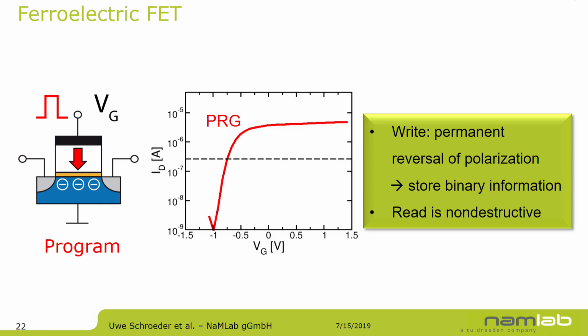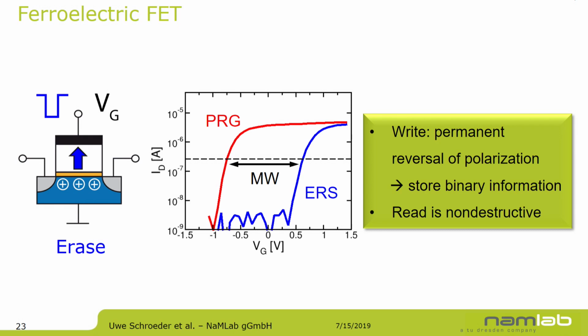And then the polarization within the hafnium oxide would impact, of course, your channel region. You would have a different charging of your channel region, and depending on that, you would have a different turn-on voltage of your transistor, which is called the threshold voltage. So you would see a threshold voltage shift from the one to the other polarization state, and this is the current you measure here on the drain. And the voltage would be applied to the top of the transistor structure. So you can see here we have our memory window between the two different polarization directions of hafnium oxide. With this, you can use this as a memory device. You basically look at a certain voltage, for example, and look at the current, and can check the polarization orientation without disturbing the polarization state of the material.